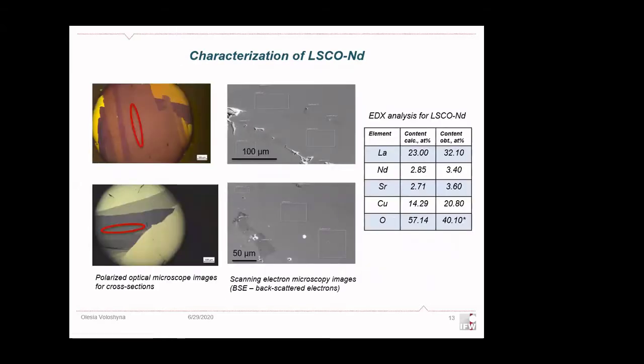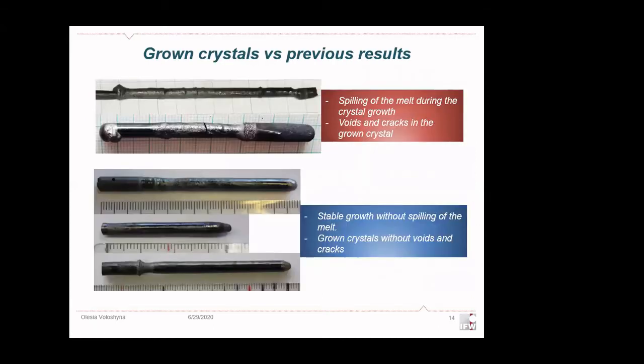And for a more precise analysis of our crystal, we use EDX analysis of the single crystal grains. And as you can see from the result, the EDX analysis proves we obtained the LSCO doped with neodymium phase.